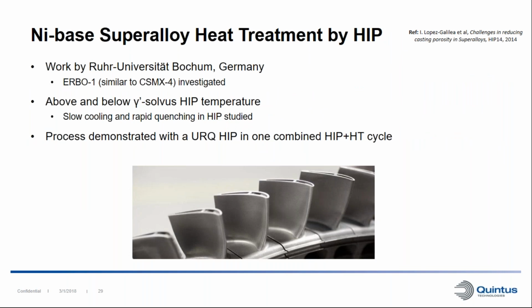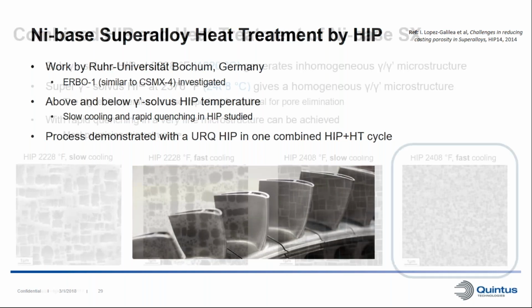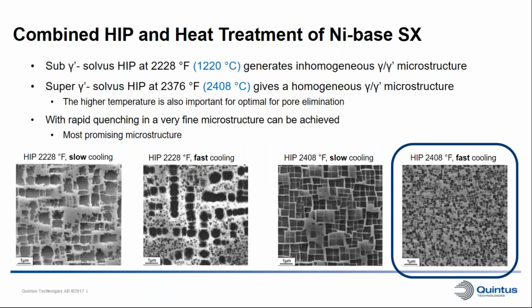Another case is for combining HIP and heat treatment for nickel-based superalloys. There's a university in Germany, Ruhr University in Bochum, that's working a lot on this topic. They have their own URQ HIP there. And this is a study that I will show a little bit about. They're looking at an alloy called ERBO-1. And they were investigating above and below gamma prime solvus temperature hipping. And they also investigated slow conventional cooling in the HIP and rapid quenching in the HIP. So here we can see the results from this study.